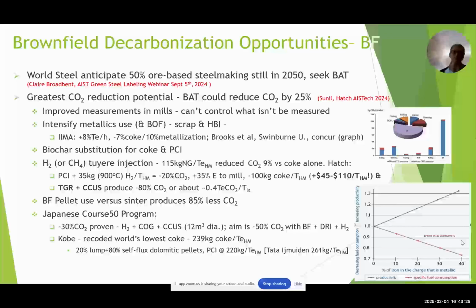There's a Japanese COURSE50 program. They've proven a 30% reduction already with hydrogen, coke oven gas, and CCUs on a 12 cubic meter furnace. They're anticipating they can hit 50% with blast furnace, DRI, and hydrogen. Kobe, as I said already, is down to 239 kilograms of coke.